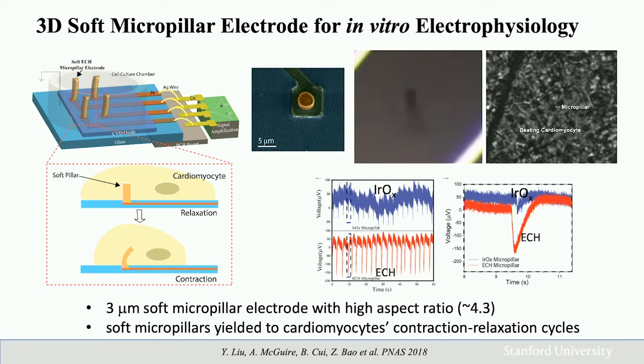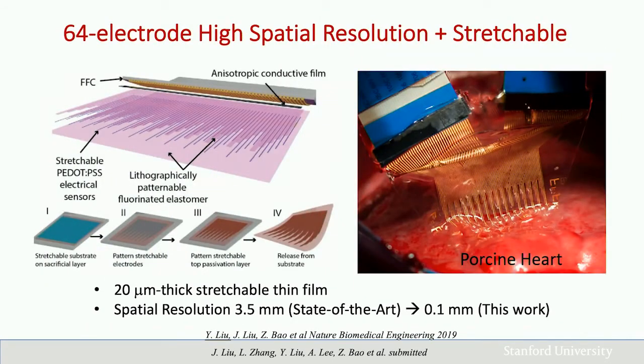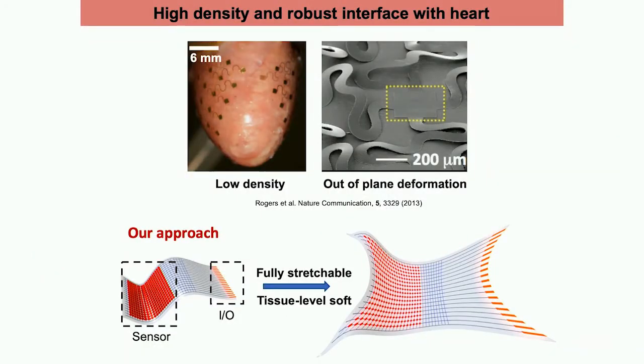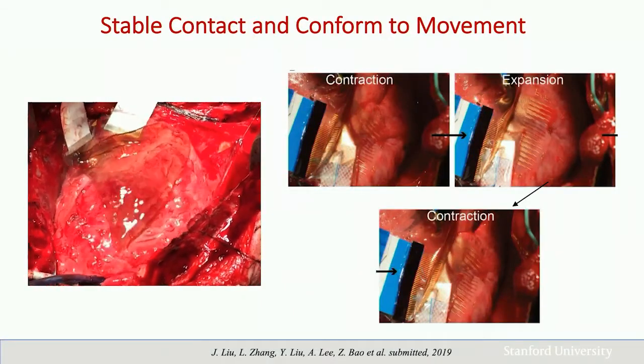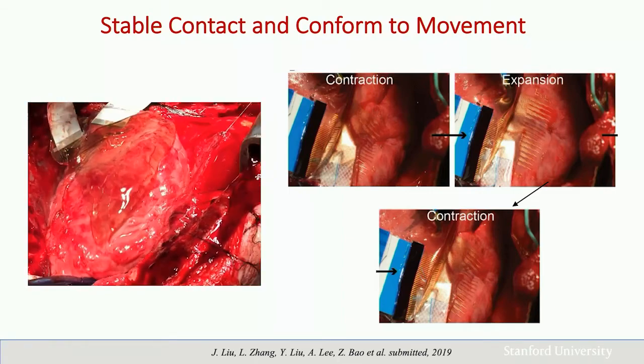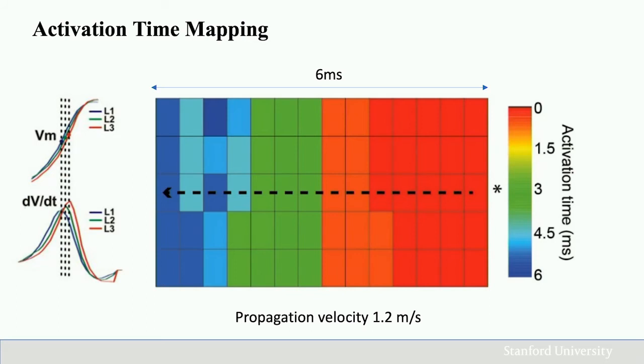And they can also be fabricated into these large sheets of stretchable sheets that have high resolution electrodes that can be directly mounted onto, this is a pig heart, but the resolution can be as high as a single cell, cardiomyocyte level. And compared to the previous approach where you have to use some serpentine structure to connect the individual electrodes, the space needed to accommodate these serpentine structures can reduce the density one is able to achieve with these kinds of electrodes. So the high resolution and also high stretchability allows us to put these high density electrode arrays directly onto the beating heart to map information at very high speed and high density.